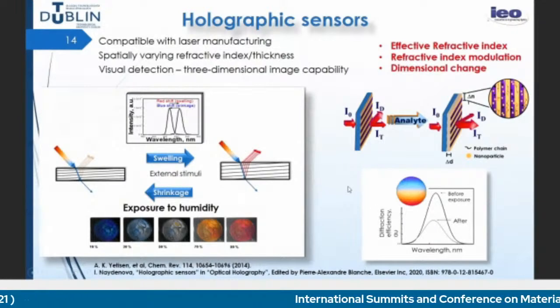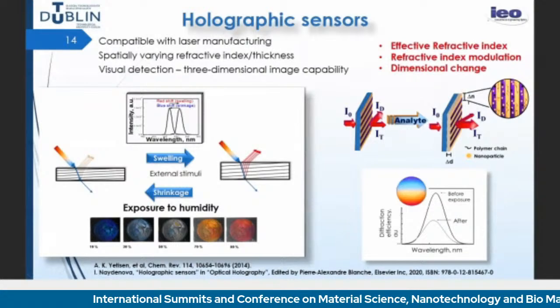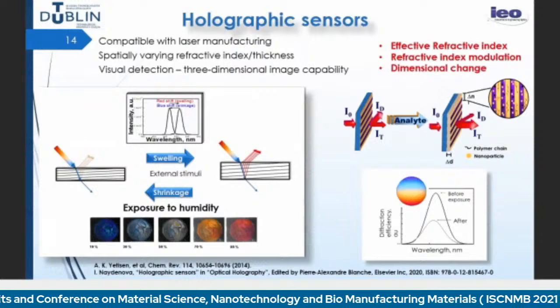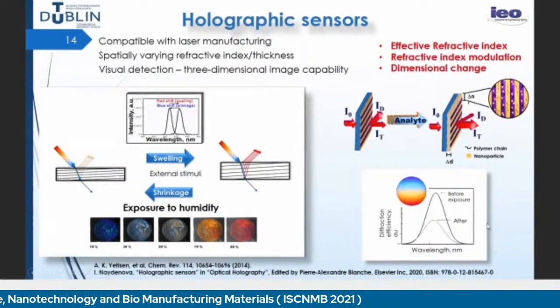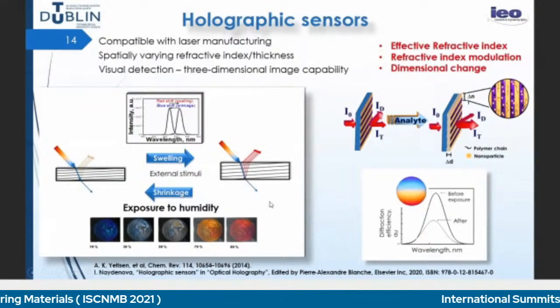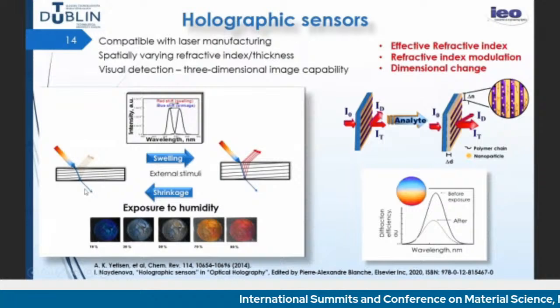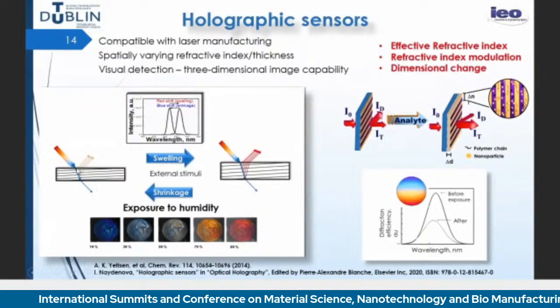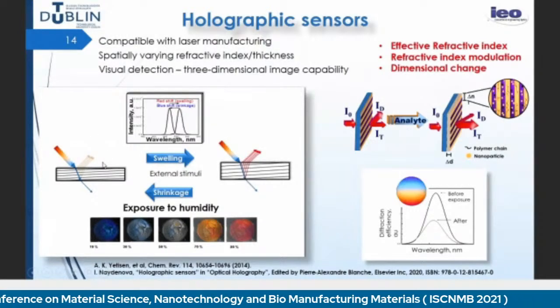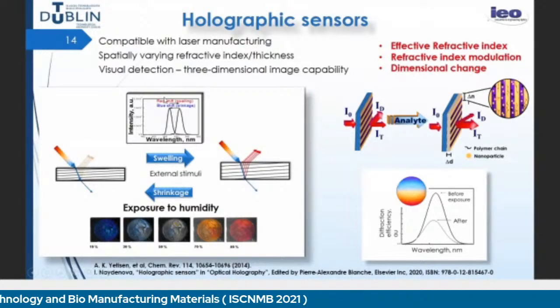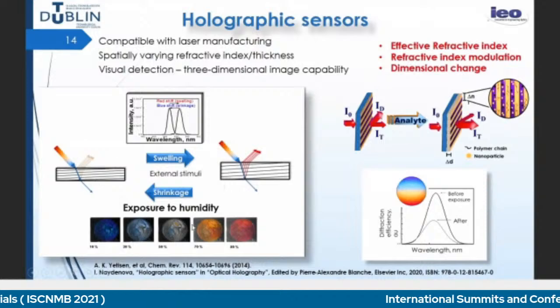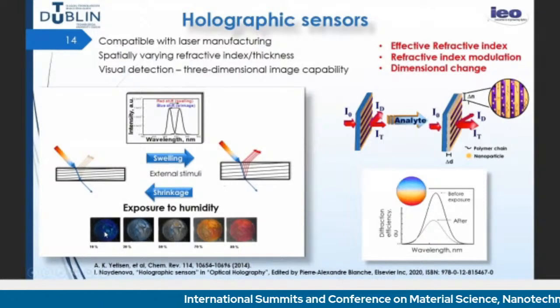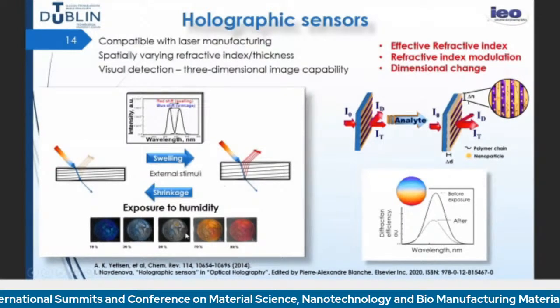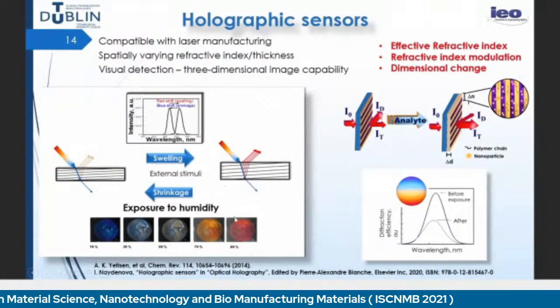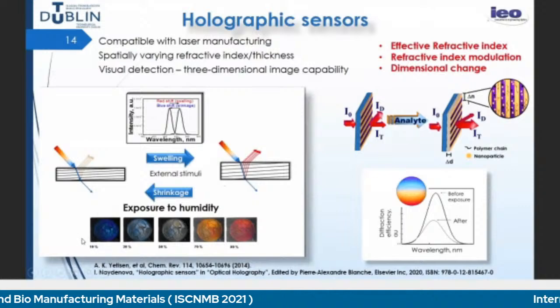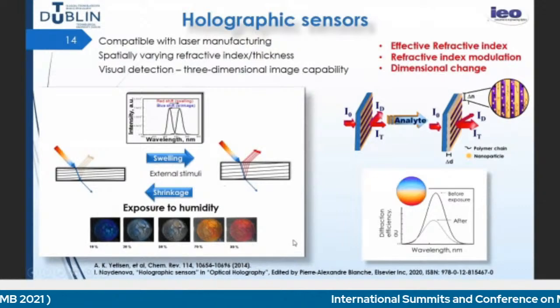So the holographic sensors are simply holograms that can change their properties in the presence of external stimuli. We use two types of sensors, one in reflection mode and one in transmission mode. In reflection mode, the sensing happens due to swelling and shrinkage of the structure. You can imagine that a reflection hologram operates as a Bragg stack, and depending on the period of the Bragg stack, a specific wavelength will be reflected, which can be observed visually or tested spectroscopically. When we have swelling, for example exposure to humidity, the structure absorbs moisture from the air. It was recorded in green. When exposed to 80% humidity, it becomes red, and if it is dried, then it becomes blue. So it can cover a different range of relative humidity in the air and indicate it visually.